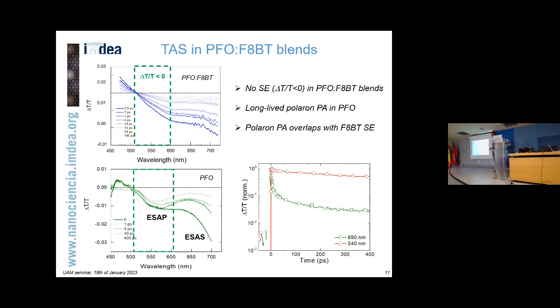So in summary, if I generate a residual of this long-lived absorption species, this absorption will overlap with potential stimulated emission from F8BT, and that causes the loss of stimulated emission.